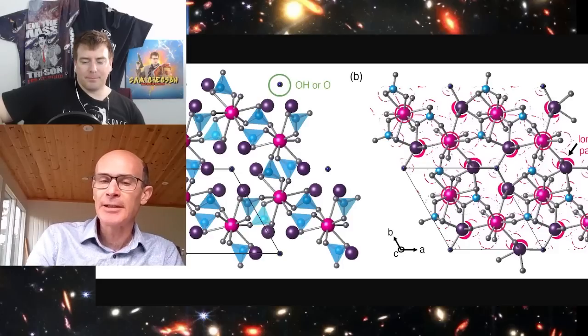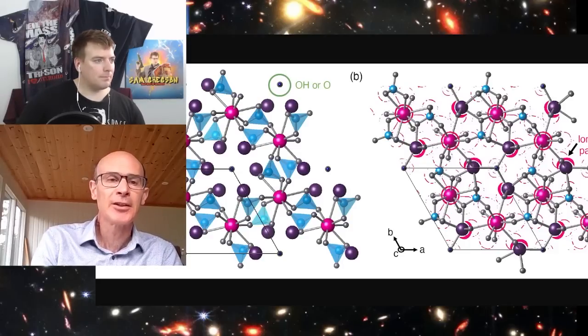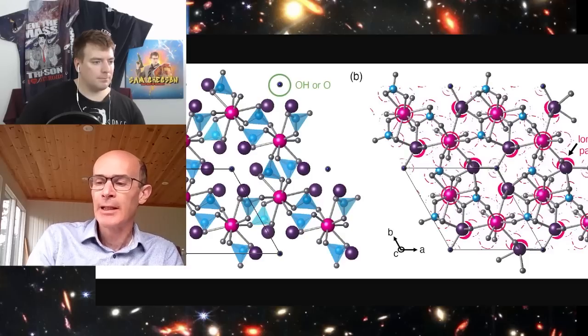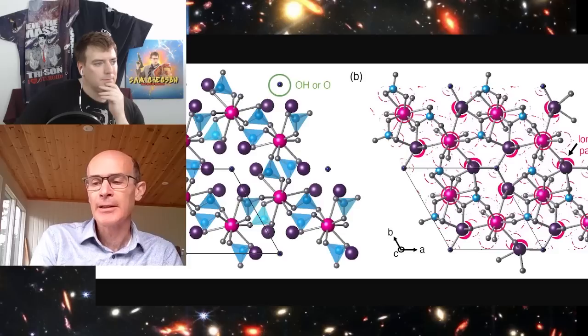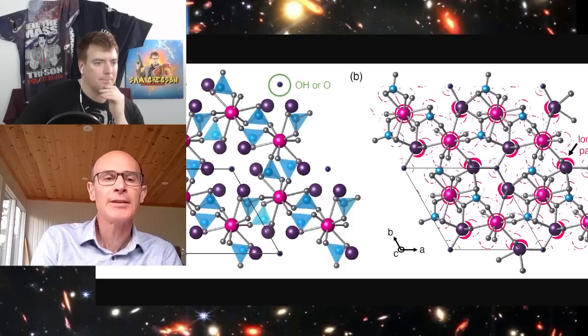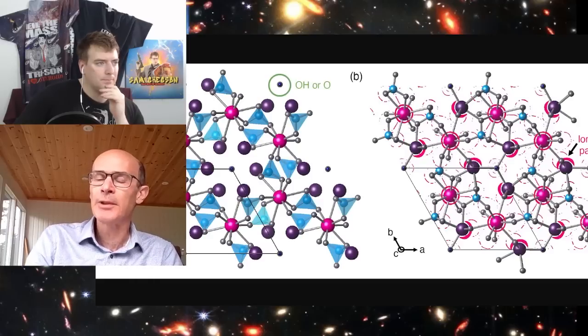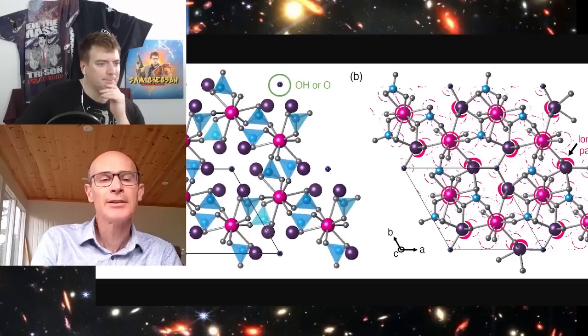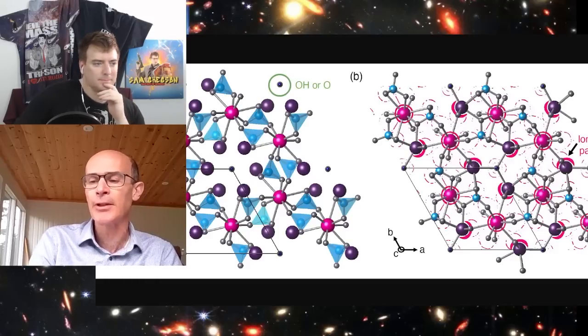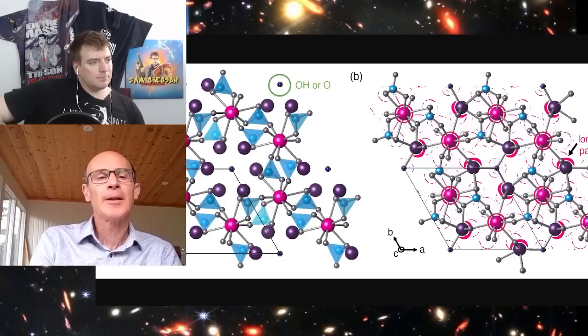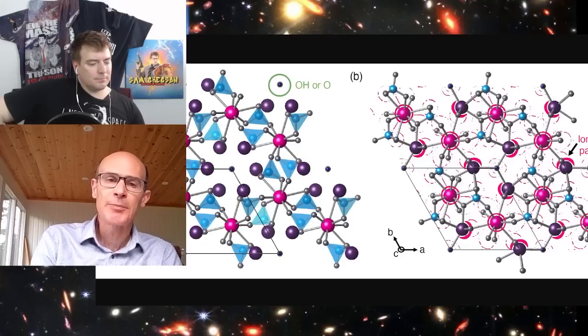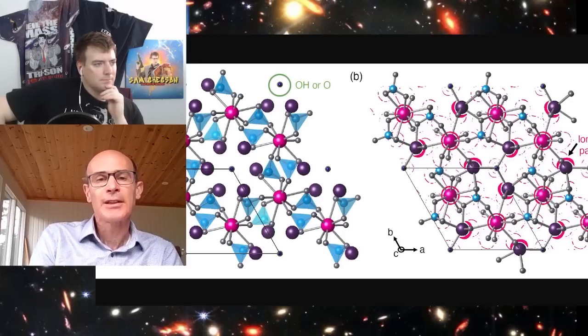So the lead apatite would be one of these diamagnetic insulating compounds, and what's been done apparently in LK-99 is that people have tried to replace some of the lead ions by copper ions, about 10% of them. I have to say that it's not been proven exactly what they've made in this case. There's very little characterization of the crystal structure. It's clear that there's a compound with the apatite structure, but the synthesis that's been described is a slightly unusual synthesis, if you wanted to make the compound that is claimed.